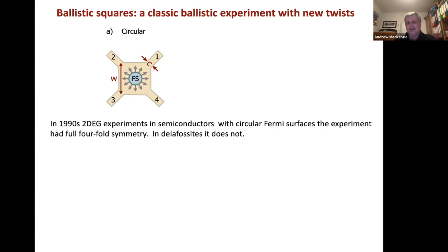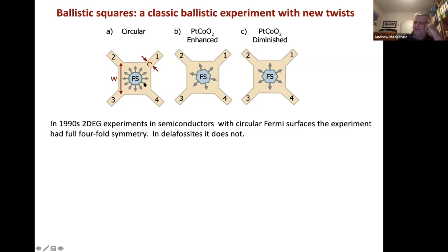Now, obviously, if you have a very high symmetry situation of a circular Fermi surface, then the total symmetry of your situation is going to be determined by the symmetry of your device, which would have been made either by lithography or gating or both in the semiconductor days. And if the device is a square, it would have all the symmetries of a square. However, when your Fermi surface is a hexagon and not a circle, then the situation you end up with is not going to have all the symmetries expected of a square.